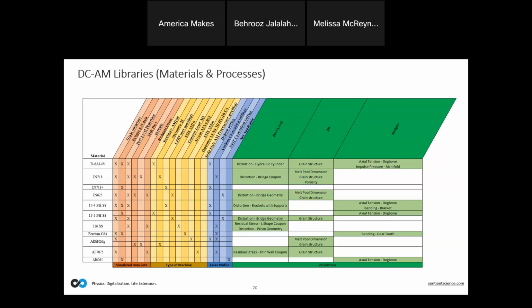At the same time, the damage mechanics solver is calculating damage for all of them. And with repetition of the load, each of them is getting more accumulated damage until one of them, or maybe a few of them at the same time, reach the critical damage level. Then there is a macro crack created there. So again, they are all available there. They are competing with each other. They are all accumulating damage. And once the damage passes the criticality, the first macro cracks are created, causing even more stress concentration. And of course, with the repetition of the load, those cracks are growing and causing the failure.